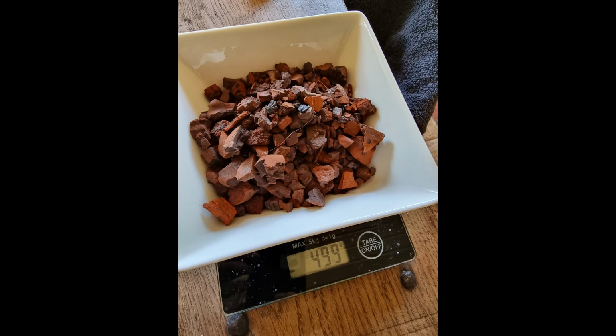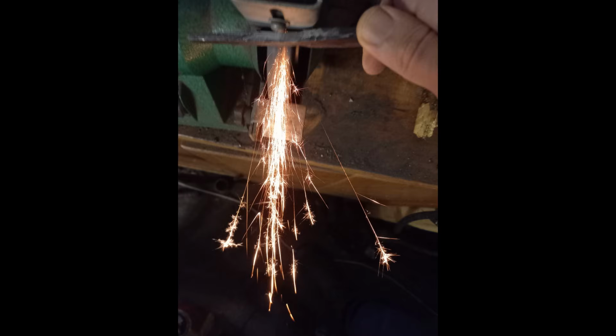But just as importantly, other specific elements that are not found in this ore are also not found in the Ulfbert swords, giving a double confirmation that this type of iron ore was very likely used for the production of the Ulfbert swords. The unique combination of 3.5% manganese with a high content of iron and a very low phosphorus